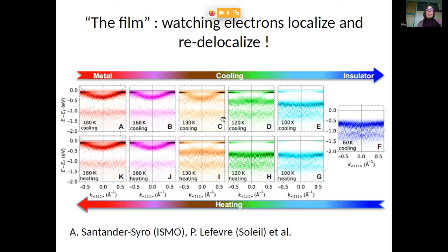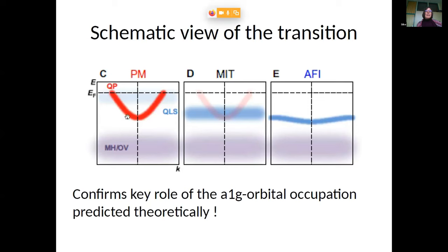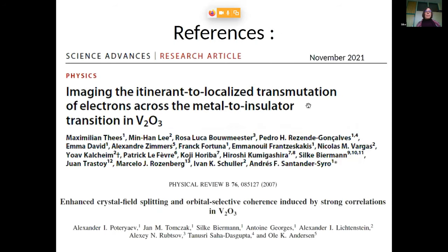At the same time, you pile up spectral weight here at these lower energies, which form just the Hubbard band in the insulating state. And when you go back, you do the inverse process, but a little bit shifted. So here you have more than you would have here. So this is indeed corresponding to the picture that in the metallic phase, you have the A1G band, which is carrying a little bit of charge, which is missing to half filling in the EG pi band. And eventually in the insulator, you go to half-filled EG pi and an empty A1G orbital occupation. Okay, and that was then this imaging of the itinerant to localized transition of the electrons in V2O3.